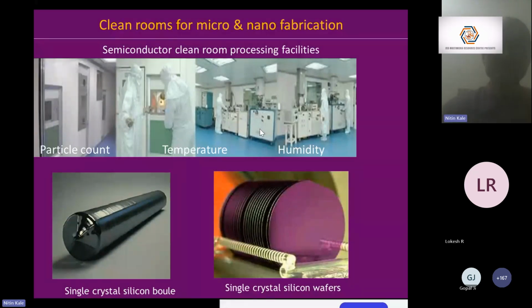On the right-hand side, what you see are silicon wafers. Silicon wafers are made from single crystal silicon boules, and these boules are generally made by the Czochralski process, where you start with a seed crystal and a silicon melt, and then you draw the crystal out from the melt. Because of quantum mechanics and the crystallography of the process, the material that comes into the boule has exactly the same orientation as the seed crystal.